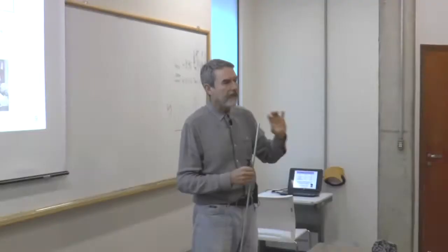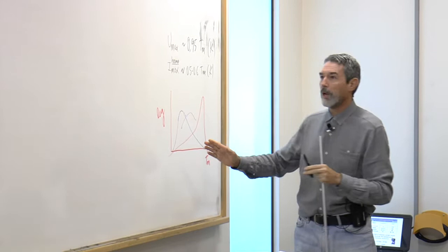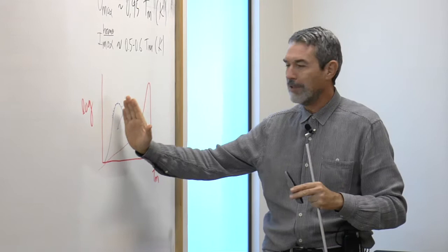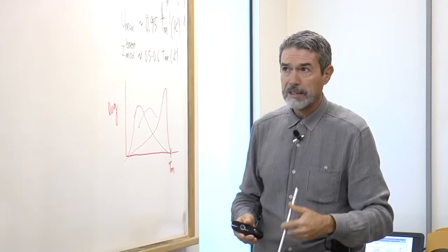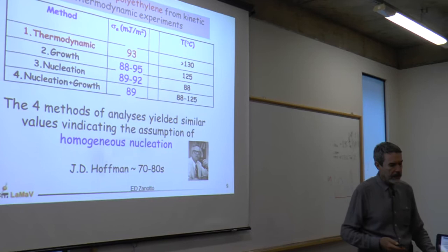I'm going to explain how you can estimate the surface energy, but they agree. And if these surface energies were different, the peak position would change a lot. The peak position is very, very sensitive to the surface energy. So this is another set of experiments which vindicate the assumption of homogeneous nucleation taking place in some glass-forming systems.